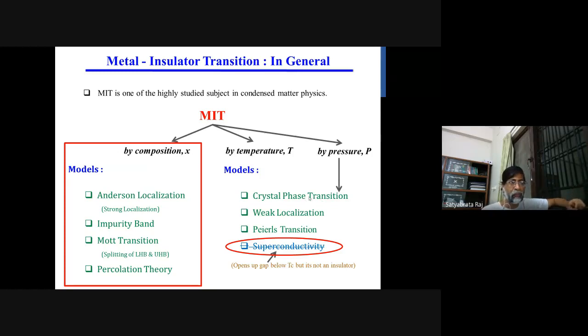And in the Peierls transition also you will have a gap because it's the insulating phase. But in superconductivity, though it actually develops a gap, it is not going to an insulating state, but it is going to a superconducting state. Peierls transition also develops a gap, and superconductivity develops a gap, but this is the difference in the superconductivity.